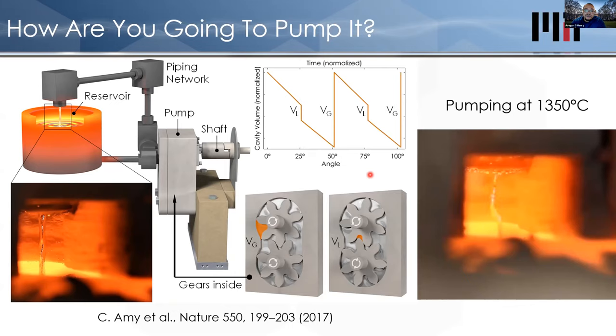It kind of is, but we can do it. So one of our big steps forward was in figuring out that you actually can make a mechanical pump out of ceramics, that we can join ceramics and make leak-tight joints for liquid metal. What you're seeing here was an experiment we did where we were pumping liquid tin at almost 1400 degrees C.